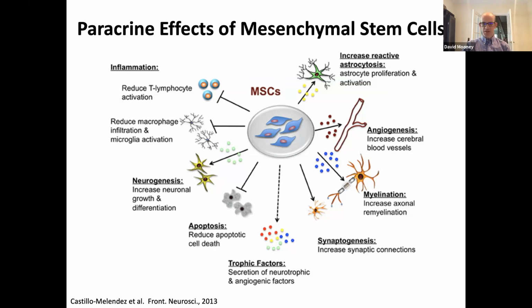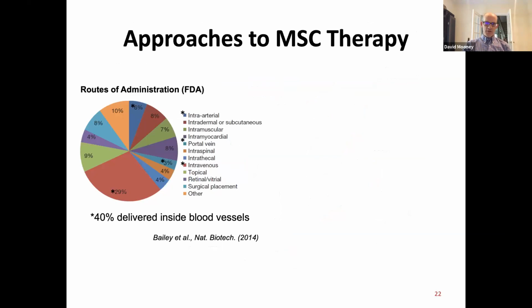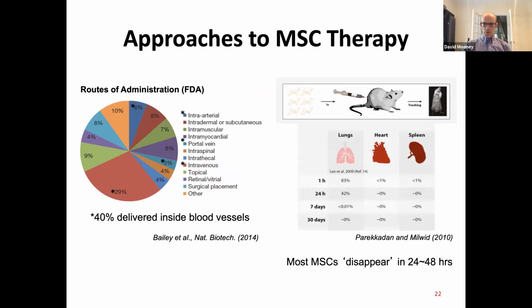A challenge with the clinical translation of these cells, though, has been that while there's a variety of routes of administration, intravascular is the dominant approach. And what one sees with that route and virtually all the other routes is that the cells rapidly disappear after injection. What's typically done is they're put into solution with a carrier fluid and injected locally or into the vascular system. But then within about a day, the vast majority of the cells, 99% or more, are gone. So it's hard to have a biological effect if the cells of interest aren't there very long, and that probably underlies a lot of the disappointing clinical trial data to date with these cells.